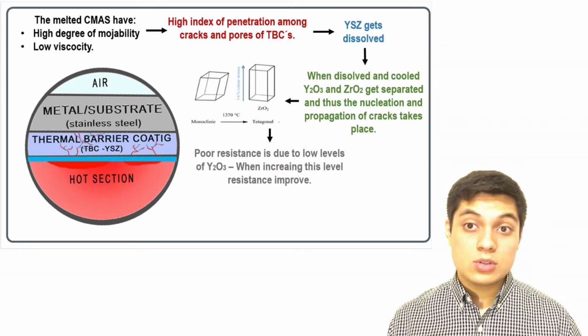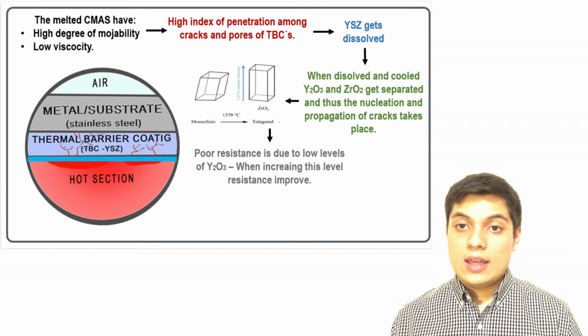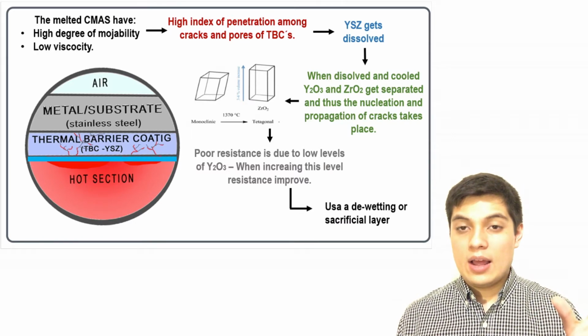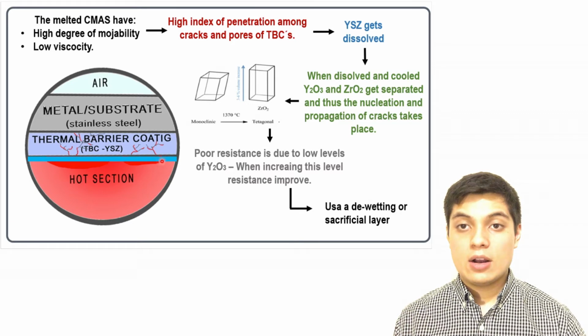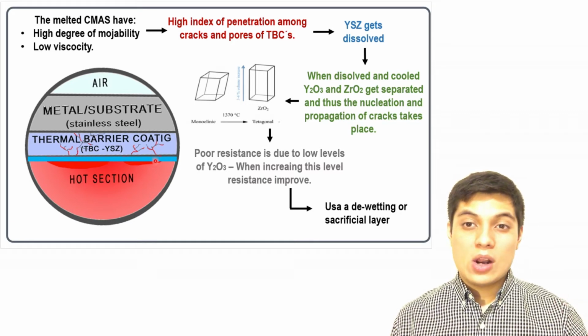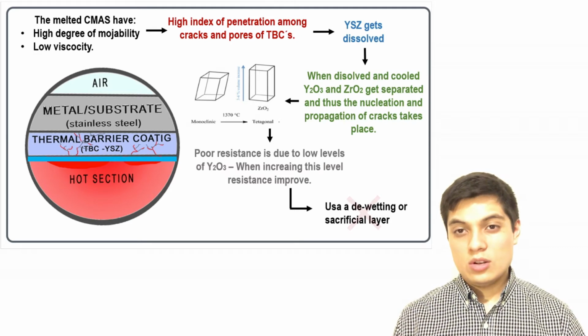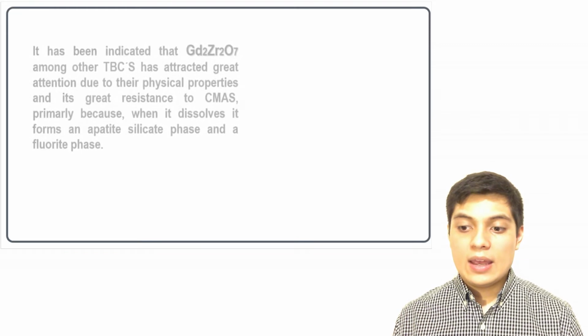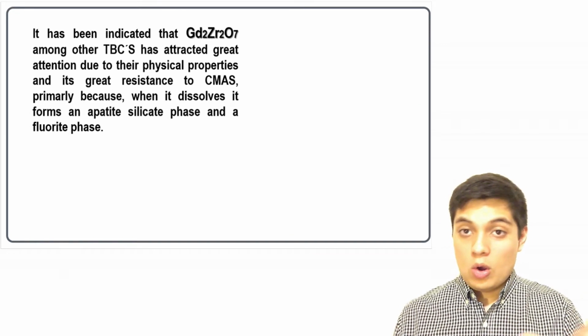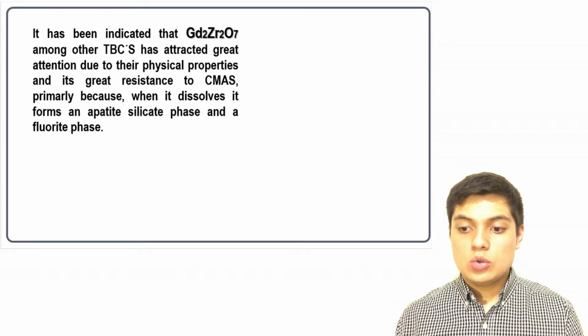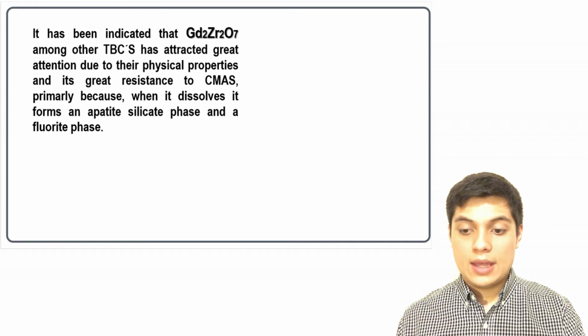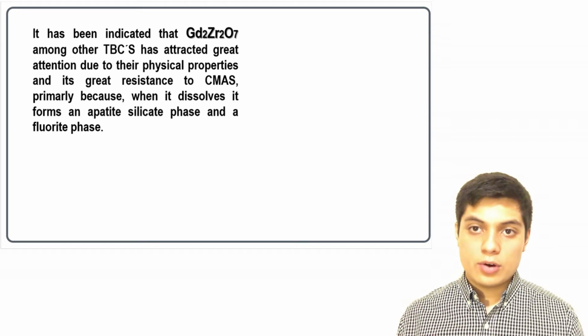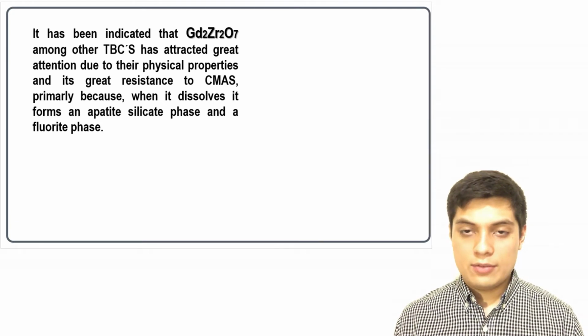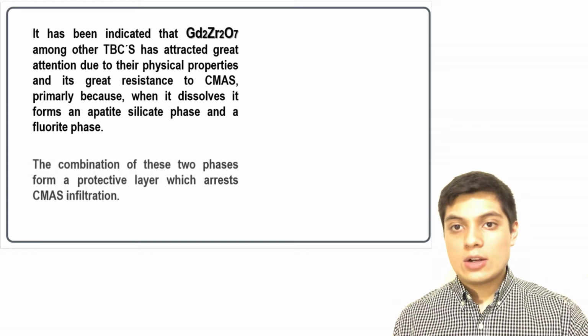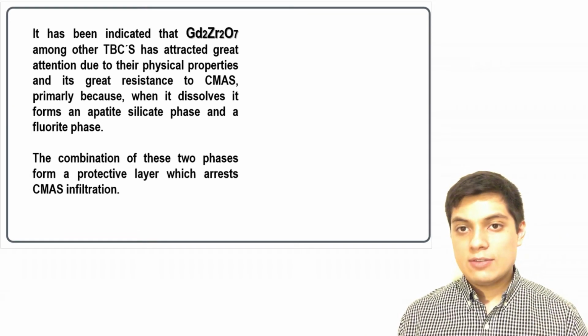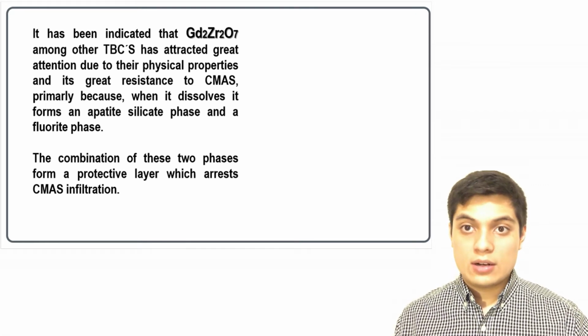So there have been some improvements among these thermal barrier coatings, and they consist of the use of a de-wetting or sacrificial layer that covers the thermal barrier coating, but in the long term this is not a good solution. So that is why gadolinium zirconium oxide, among other TBCs, has attracted great attention due to its physical properties and its great resistance to CMAS, primarily because when it dissolves, it also forms the apatite phase and the fluorite phase. And when these two phases are combined, the fluorite one and the silicate one form a protective layer that arrests the further attack of the CMAS.